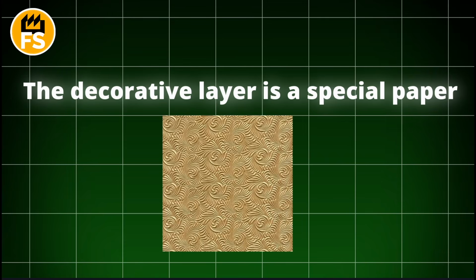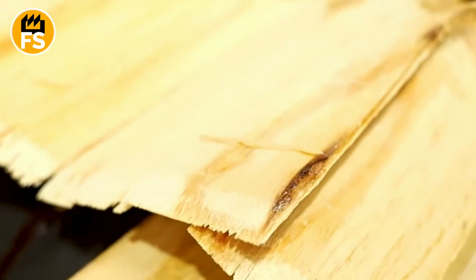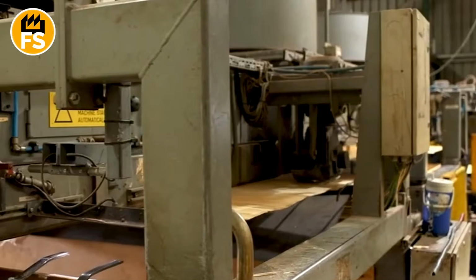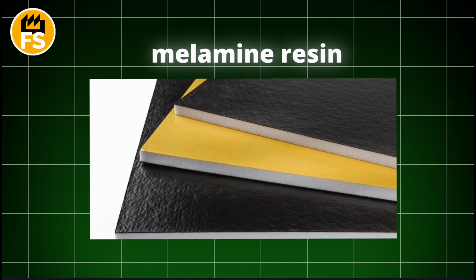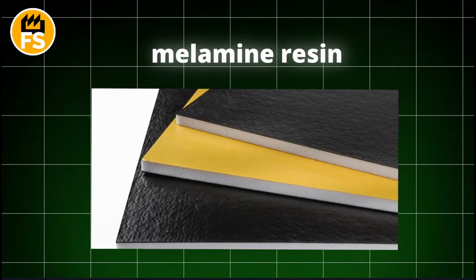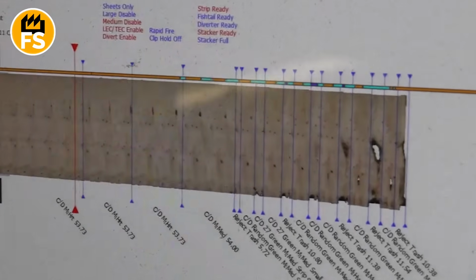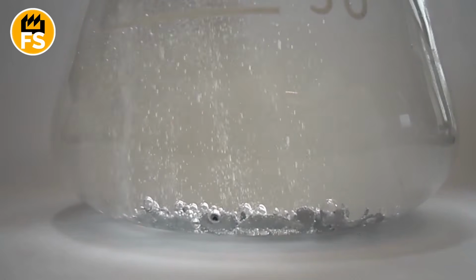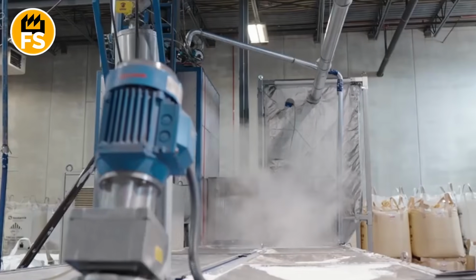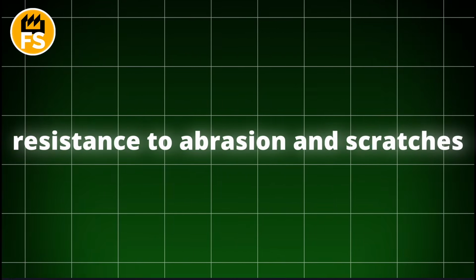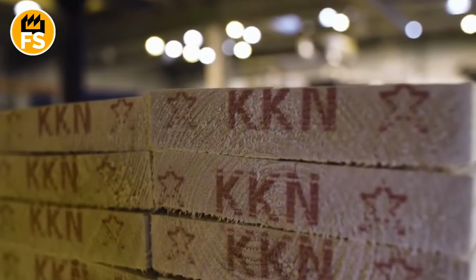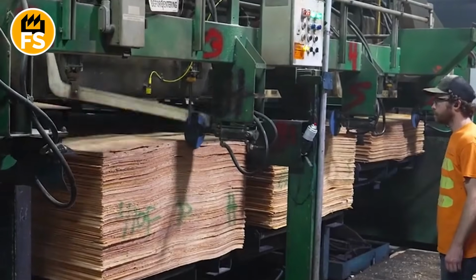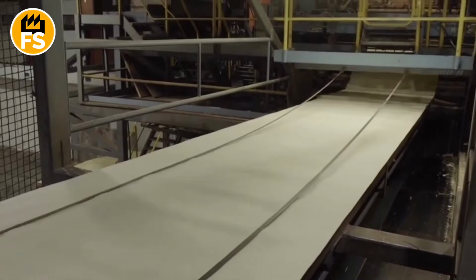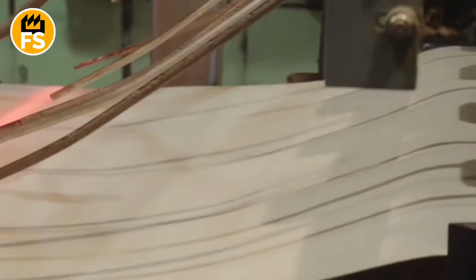The decorative layer is a special paper on which a printed pattern is applied, imitating wood, stone, or another material. This paper is impregnated with melamine resin, which, after polymerization, gives it hardness and wear resistance. The protective or overlay layer is also paper, but it is impregnated with an even greater amount of melamine resin and small particles of aluminum oxide. Aluminum oxide, which is a very hard material, gives the laminate its main property: resistance to abrasion and scratches. The thickness of the protective layer is only a few thousandths of an inch, but it performs a critical function. Both of these impregnated paper layers are dried and stored in rolls until the pressing moment.